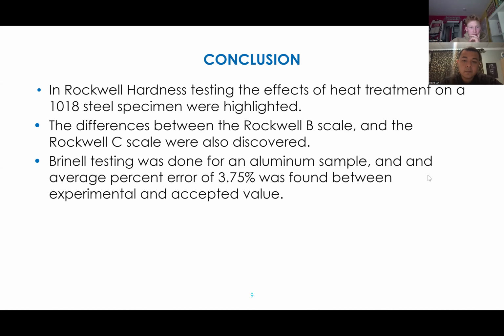And to conclude, for our hardness testing, we were able to see the effects of different heat treatments on a 1018 steel specimen and see how they would react under different loads and different hardness tests. We also found the differences between the Rockwell B scale and the Rockwell C scale. It was very apparent in comparing the values we got for our 1018 with the different heat treatments on the Rockwell B and the Rockwell C scale. And then for Brinell testing, we learned how to use a Brinell testing machine, but we were also able to yield good data, finding an average percent error of 3.75%.